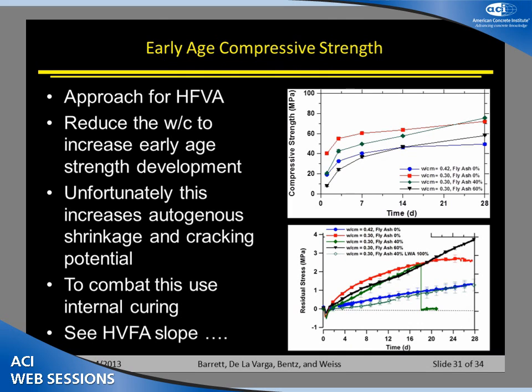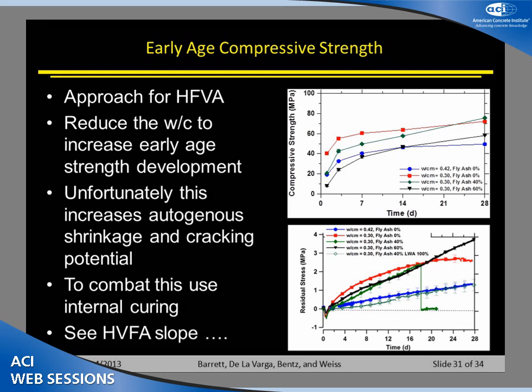The other thing that we've been doing when we've been looking at the high volume fly ash systems is, and you'll see this here, we've got a 0.42 water to cement ratio concrete. This is a fairly typical bridge deck mixture. And in order to make the materials have similar strength development at very early ages, this green line shows what happens if we replace 40% of the cement with fly ash. This dark black line here shows what happens if we replace 60% of the cement with fly ash. The difference here is what we've done to offset some slower early strength development is we've reduced the water to cement ratio. So we can reduce the water to cement ratio. We can get very similar performance at 1 day with 40% of the cement being replaced with fly ash.